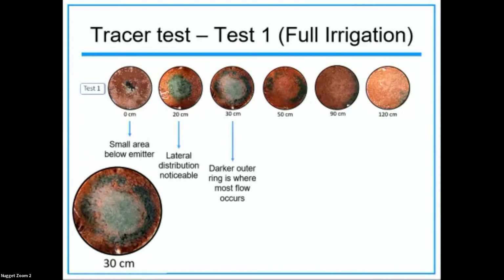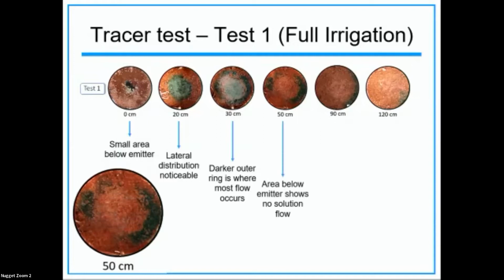But then by the time we get to the 30 centimeter, that center of the core had started to fade and go away. And then we're seeing this ring of solution on the outside. And then when we're down to 50 centimeters, we don't see any solution going through the center of the column, and all the solution is being pushed to the outside.